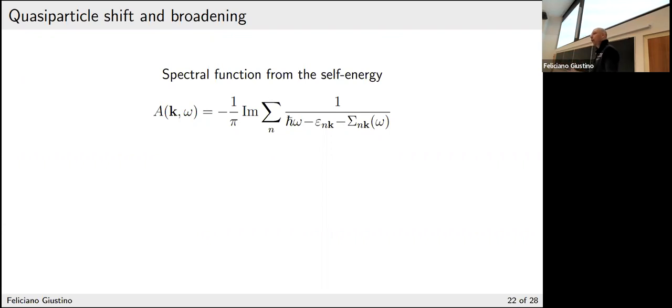Then there is also an aspect of phonon-electron interactions where, let's say, one can take phonons from density functional perturbation theory. Those will be non-interacting in a sense, but one can still build interactions with the electrons using exactly the same language that I illustrated here, and there would be some self-energy for the phonons coming from the electrons essentially, and these things lead to lifetimes, lead to broadening and effects like that. So all of this is doable.